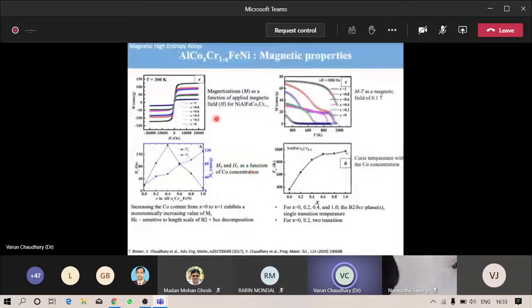These are the magnetic properties for these aluminum, cobalt, chromium, iron, nickel alloys. We see the saturation magnetization increases with increasing cobalt content. However, the coercivity first increases and then decreases. We also measured the Curie temperature: on one side it is less than 400, while on the other side the Curie temperature is more than 900.